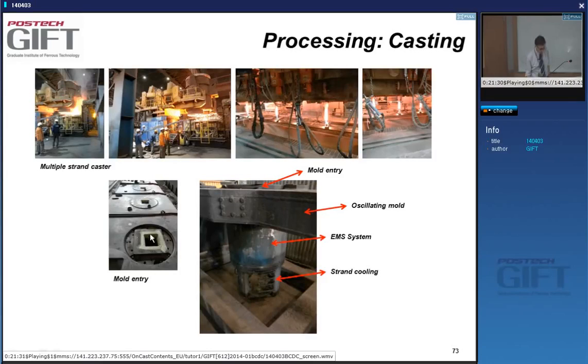If you look down this caster, it actually looks much more complex than just a piece of water-cooled copper. This here is what you see if you look on the side. You have this construction that will be moving up and down, the entry mold. Then we have here an attachment which is called an EMS system, electromagnetic stirrer. We'll talk about this in a moment. Then, already attached to the mold, you have the exit cooling of the strand. So the strand comes out, goes through an electromagnetic stirrer, and then right into the strand cooling.